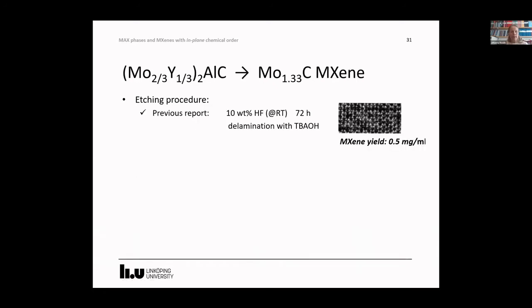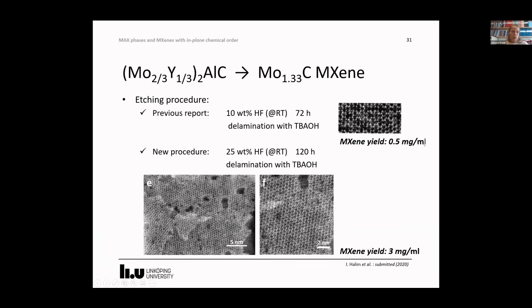So to convert the i-MAX into MXene, we previously used 10 weight% HF for 72 hours, and we got a MXene yield of 0.5 milligram per milliliter. For the new i-MAX sample, we also used a new etching procedure. And for the same amount of starting material, we now have a MXene yield of 3 milligram per milliliter, which is 6 times higher than before.